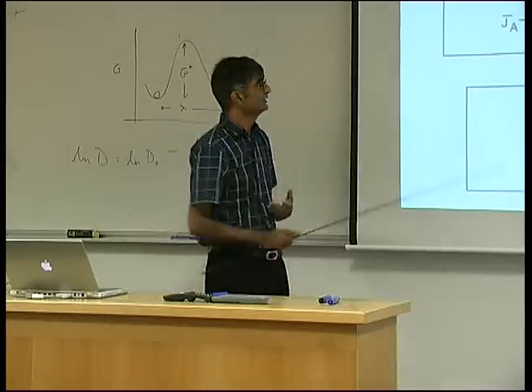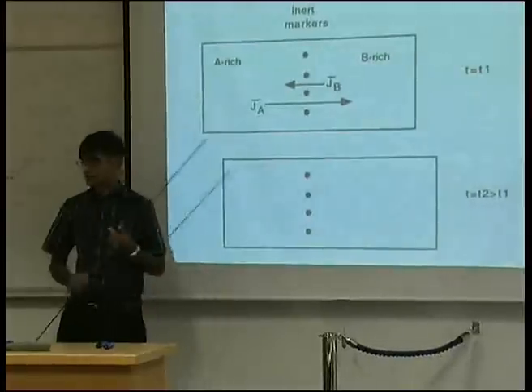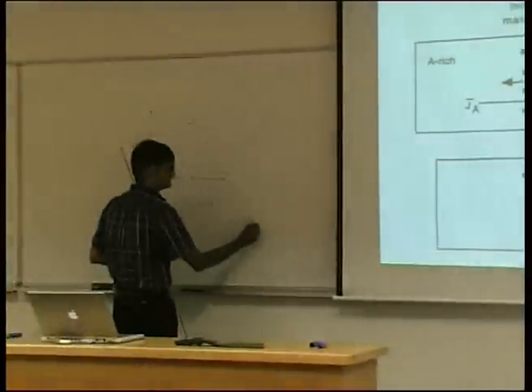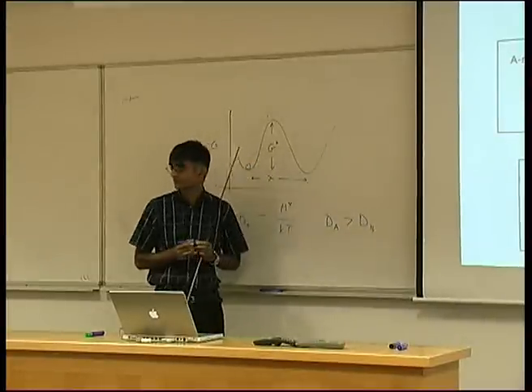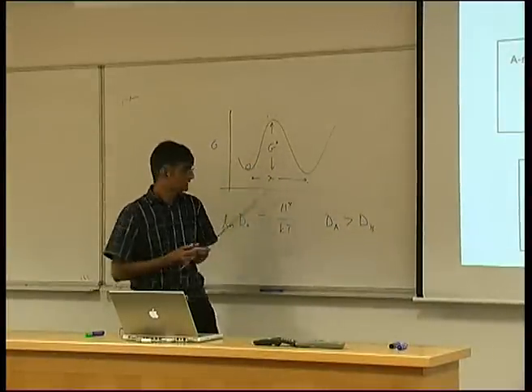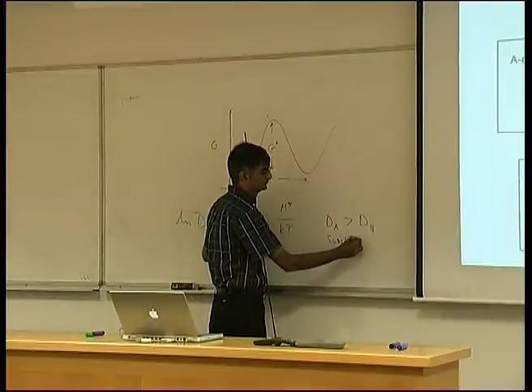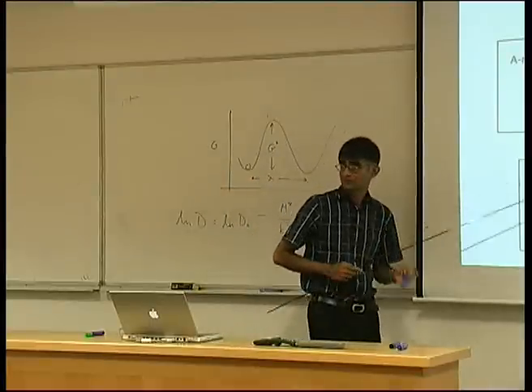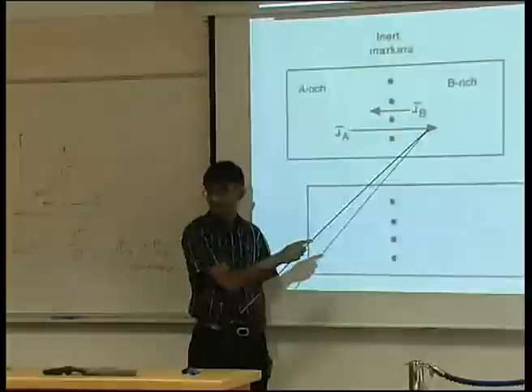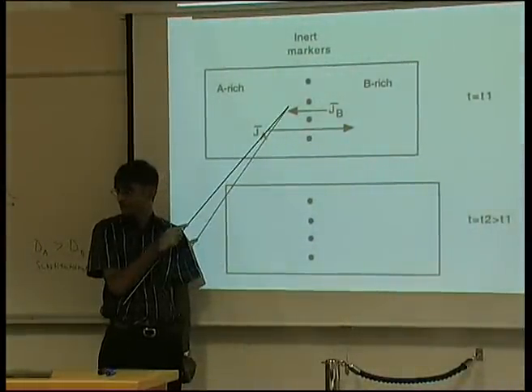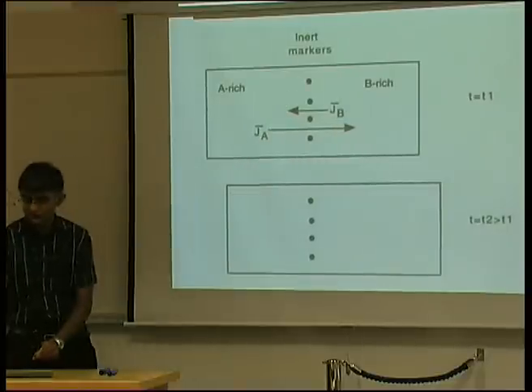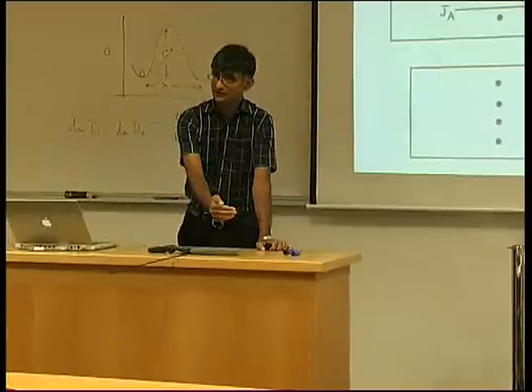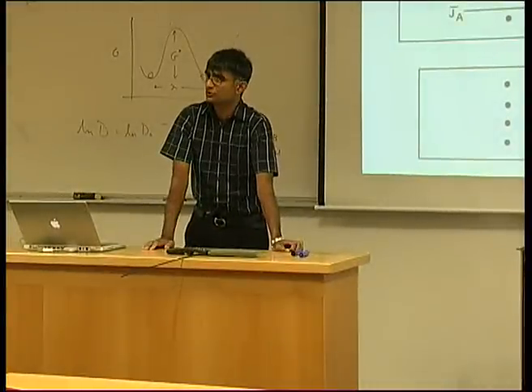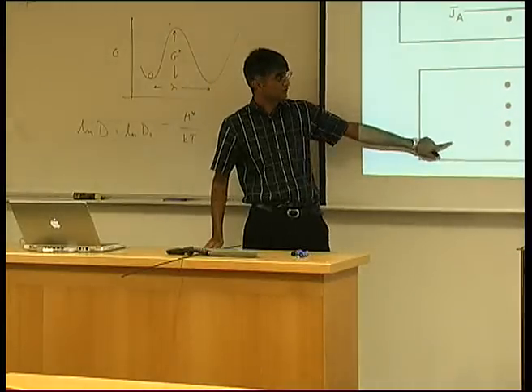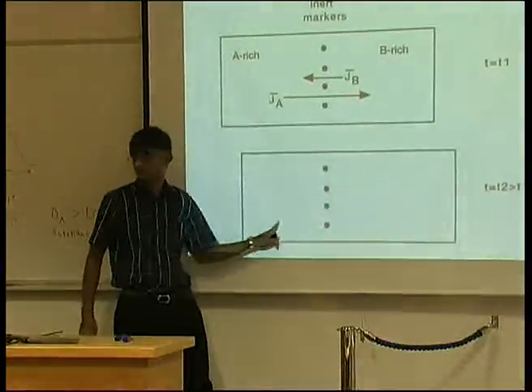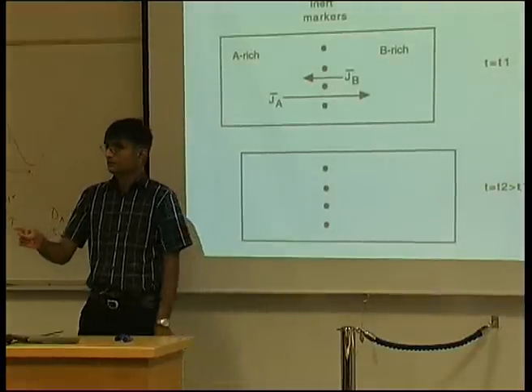And I've chosen this system so that the diffusion of A in B is faster than the diffusion of B in A. So the diffusion coefficient of A is greater than that of B. Yeah? And they are both substitutional atoms. Now, because D_A is greater than D_B, I have a larger flux of A atoms in this direction than of B atoms in the opposite direction. Right? So if this was my marker, there's more matter going in this direction than in this direction. So the whole specimen is going to move on the bench. Right? That's what's described here. You can see that I've ended up with more material on this side of the marker than on this side. That can only happen if you have a vacancy mechanism.